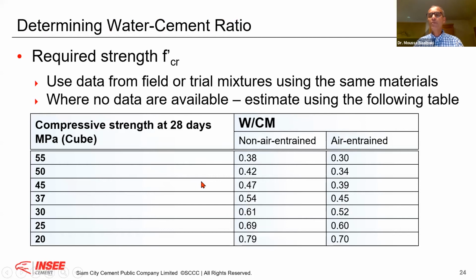Now, this is a table, for example, where you see the 28 days compressive strength on cube. Even though I took this from the ACI, I translated this number for cube. You see, for example, if I have to design a 30 megapascal concrete, I can work with 0.61 water cement ratio. Now you understand in Sri Lanka, for example, very often when people design for the bad market, when people go for 20 megapascal or 25 megapascal, if you do the real calculation of the water cement ratio, very often they are above 0.65. Because yes, of course, you get this compressive strength, but the durability of those concretes is very low, as you could see in the exposure condition.